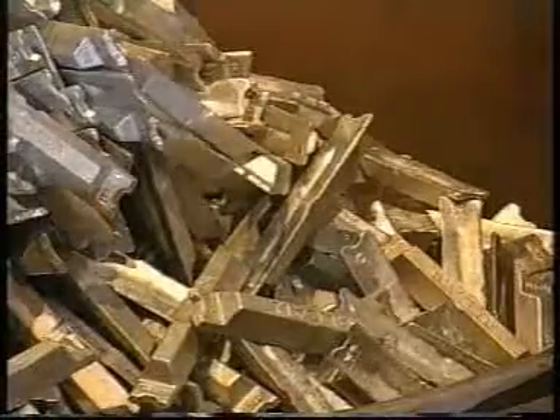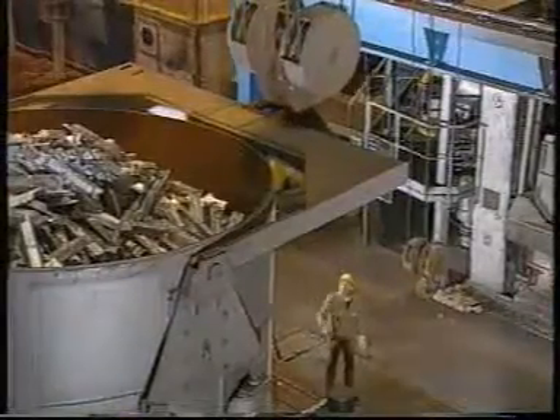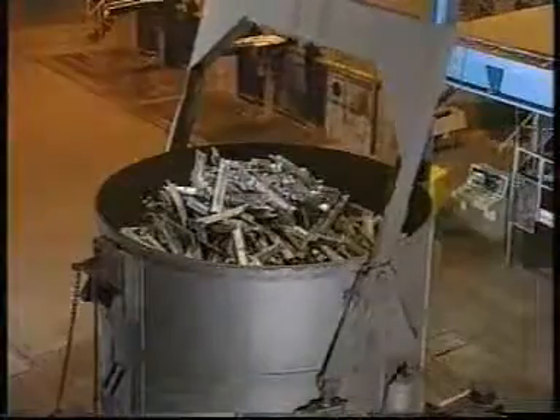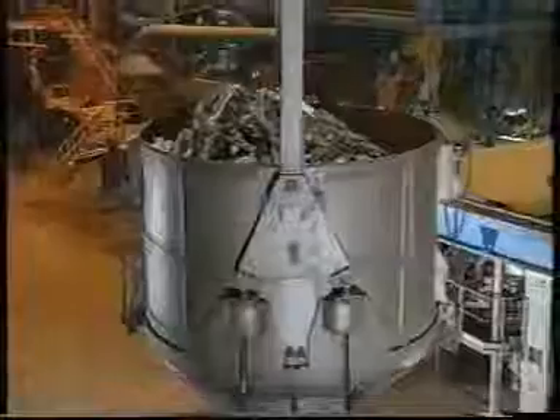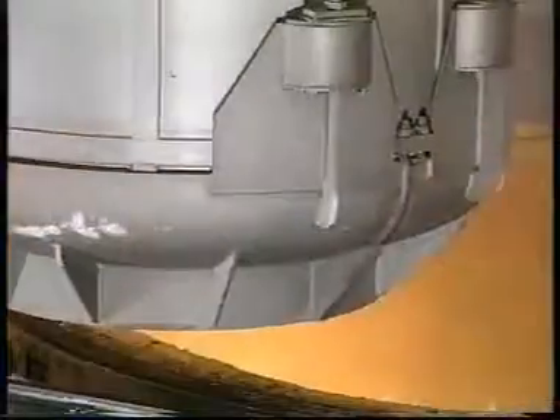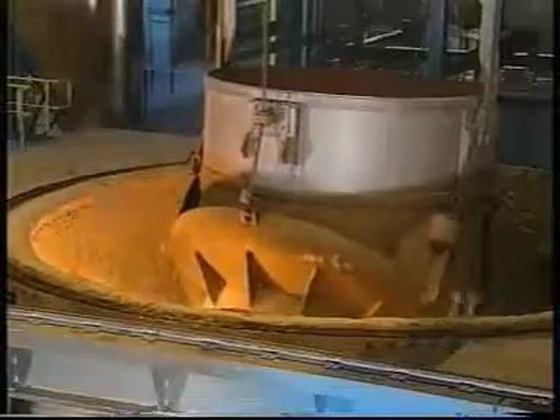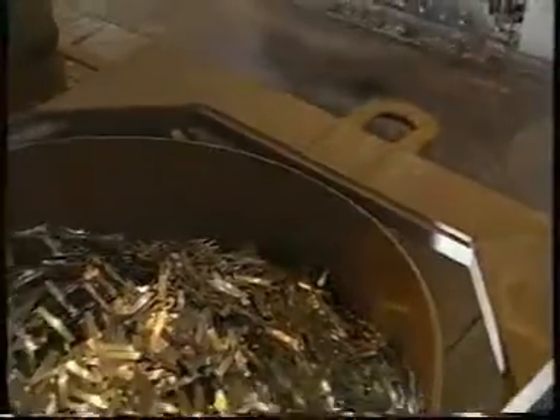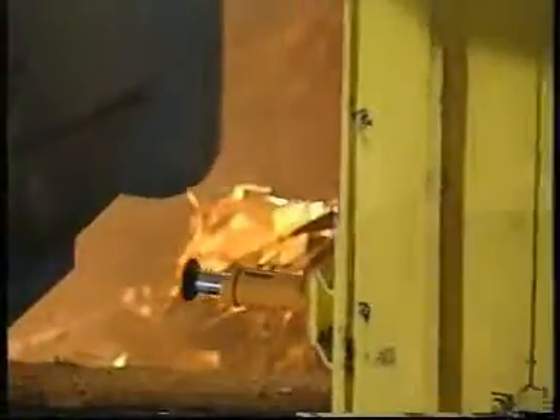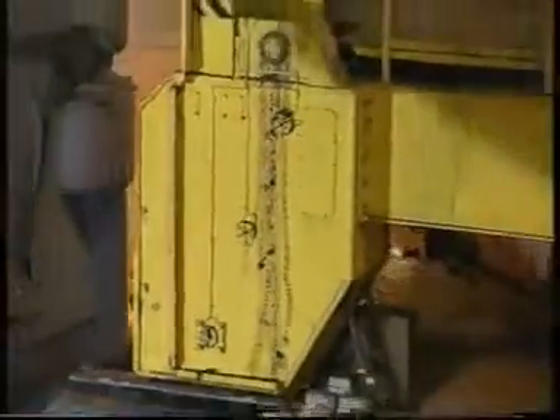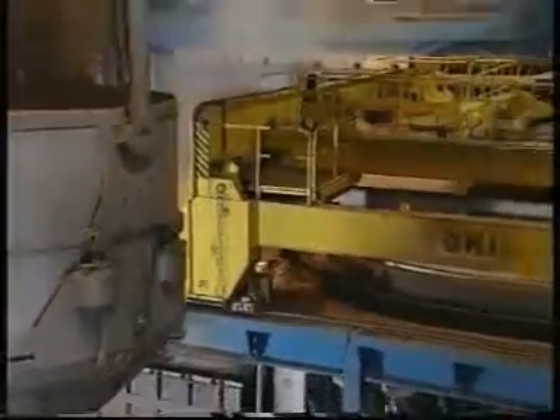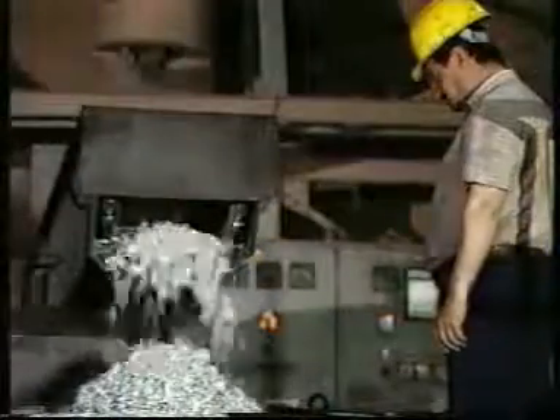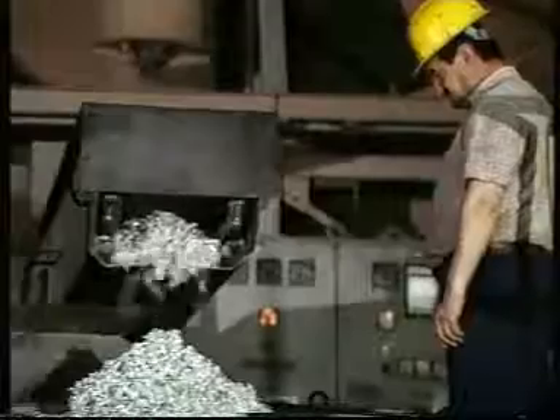The start of a fascinating production process. Aluminium pigs from all over the world and uncoated processing scrap are melted down in 13 remelt furnaces. These giants, with capacities up to 120 tons per furnace, melt up to 36 tons per hour. Monitored by a sophisticated scrap recording and cast information system. The chips from ingot scalping are melted in induction furnaces with minimal loss and fed into the cast as molten metal.